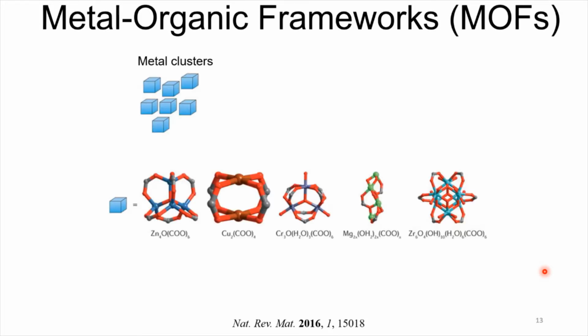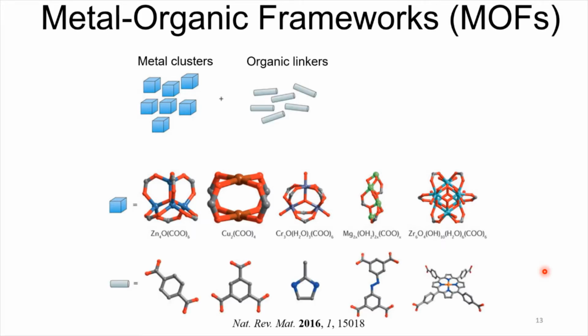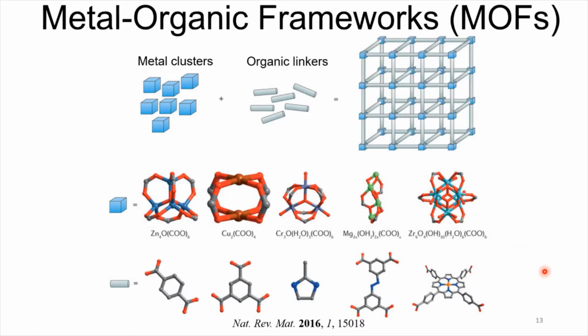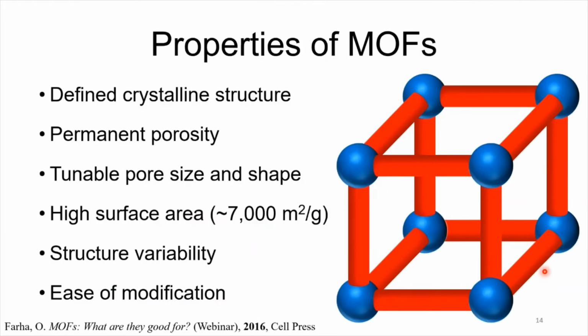Well, these are materials that are composed of metal clusters or metal atoms that are coordinated to organic linkers or ligands. And this will make extended infinite structures that are very crystalline. They are porous. And because you can choose which metals and which linkers you use, you can tune the pore size and shape. Of course, they have high surface area. There are reports of even more than 10,000 meters squared per gram.